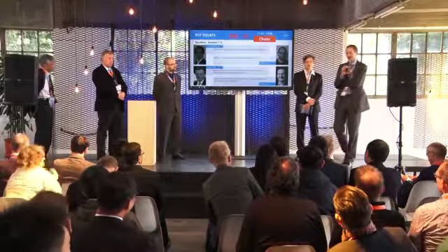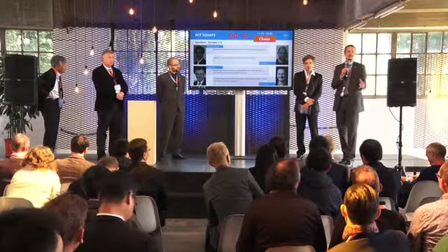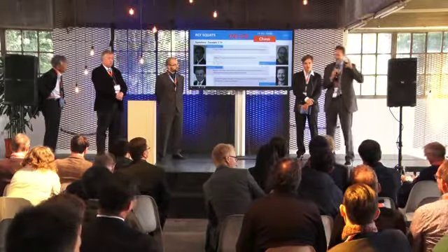That's a very good question. If you look at what we saw in the 70s, a lot of plastic deformation, definitely a ratcheting-driven defect. Here, this defect appears within 10 MGT, so ratcheting wouldn't be the cause for such a defect. Yeah, I think also Stuart published a paper on this. And so, if it's not ratcheting, perhaps it's not RCF, but I'm not entirely sure.